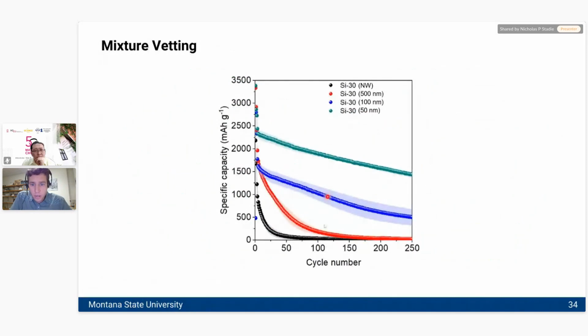When Izzy, one of the grad students in our group, tried to make other 30-70 mixtures with other random combinations of things, none of them worked as well as the original 50 nanometer, 1 micron mixture that our postdoc was able to come up with. And so this is pretty good evidence that something about a really small particle in the presence of a really large particle is what you want in this case.